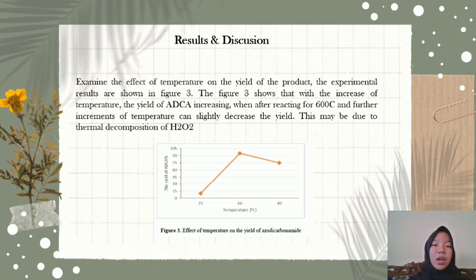Next, we examine the effect of temperature on the yield of the product. The experimental results are shown in figure 3. Figure 3 shows that with an increase of temperature, the yield of ADCA increases, reaching a maximum after reaction at 60 degrees, and further increments of temperature can slightly decrease the yield. This is due to thermal decomposition of H2O2.